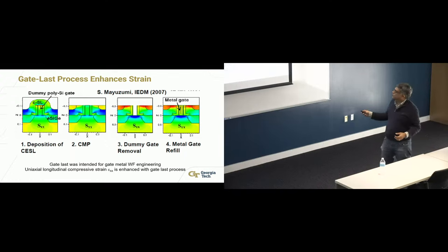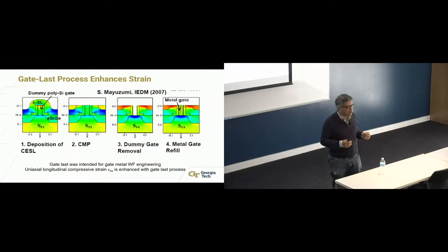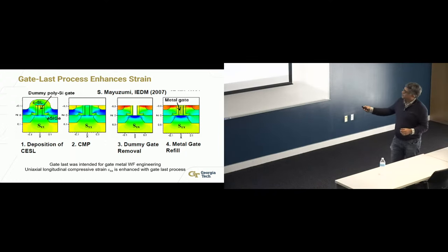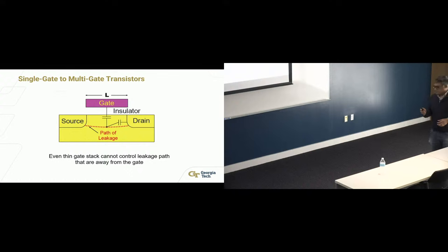Now what happened was, as soon as we did that, we saw that for PMOS, the silicon germanium source drain were already there. As soon as you take this thing off, you expose the free surface, and the SiGe source drain starts pressing even stronger. So what we found was that for the PMOS, the uniaxial compressive strain got enhanced because of this integration flow. Had nothing to do with high K or the metal gate. So this is what I say, you have to watch out for these kinds of minute effects, which can make a big difference. You can get a 30% jump in your transistor performance, which is almost like two generations of scaling. So that's what was used.